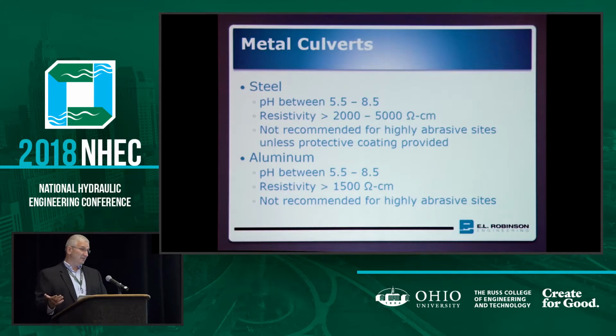And steel on its own without some sort of paving, really, really high abrasive sites, you should avoid it. You should just avoid the pipe when it's really abrasive, because without a coating, that abrasion corrosion process is just, I've seen pipes 3, 4, 5 years old that the inverts are completely rusted out and gone. The inverts are gone just because of that corrosion process.